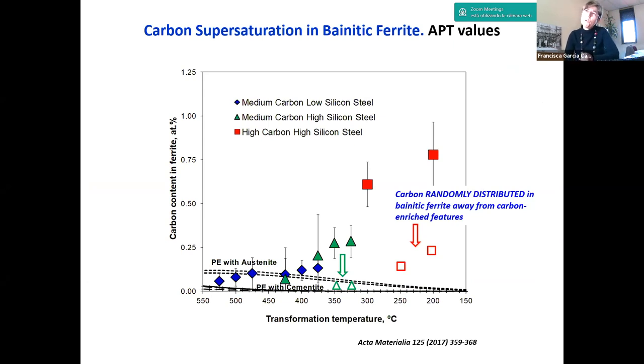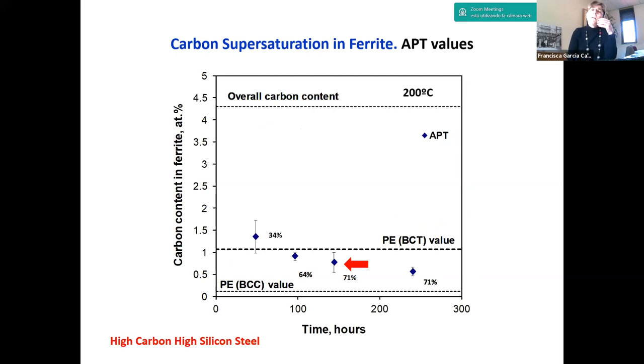Let's see the carbon content in bainitic ferrite. Originally measured by concentration profiles and proxigrams, and randomly distributed. And you can say that at temperatures higher than 300 degrees C, there are so many processes running at the same time that it is difficult to detect the carbon supersaturation during the transformation. And what we learned with low temperature bainite is that we were coming from this paraequilibrium structure, and that was approaching the equilibrium very similarly to martensite at low temperature tempering. That's what we learned. This is the evolution at 200 degrees C, evolving with time.